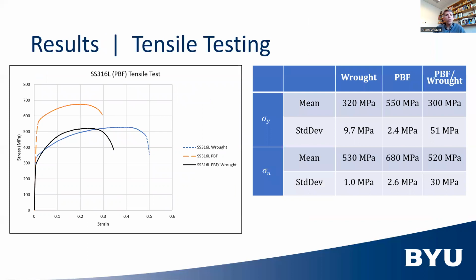So what did we find? Well, here's our results for tensile testing. We had several specimens, several samples of each variety. These are the average results. But you can see the orange is the powder bed fusion, the additive manufactured material. The blue is the conventional wrought material. And then the black curve is our hybrid half wrought, half PBF material.